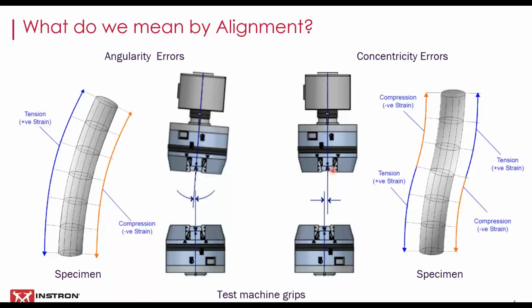So what do we mean by alignment? Well, in the center of this slide, you've got a typical testing machine load string, load cell, grips, hydraulic grips in this case. And we've got a couple of cases where you can clearly see they're not perfectly aligned. They're not completely coaxial. And we're quantifying this in two ways. We mainly talk about angularity errors, which this is a case of angularity on the left-hand side. And you can see, obviously, it is causing curvature in the specimen. So we've got an increase in the positive tensile strain on one side. We've got a compressive strain on the other side.